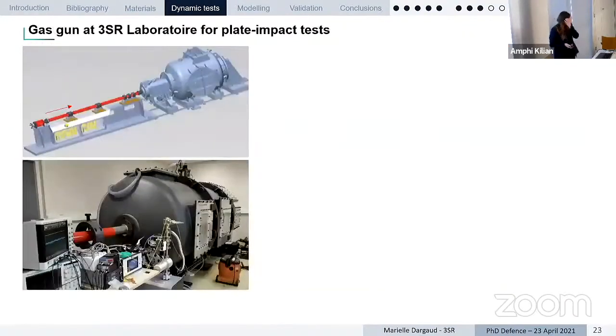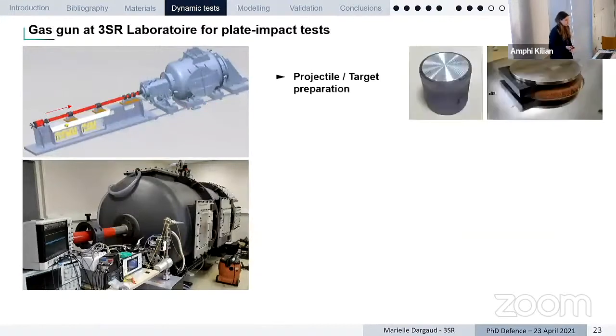The experiments are done with the gas gun at the 3SR laboratory. We perform plate impact using this launcher, where we put the projectile in here, and it is going to be launched in this long tube and impact the ceramic target in this big chamber, which is put under vacuum. Here you have images of the projectile put into a sabot and the target, on which we have put a buffer plate, which is just a mechanical filter that is going to transfer a more homogeneous loading to the ceramic.